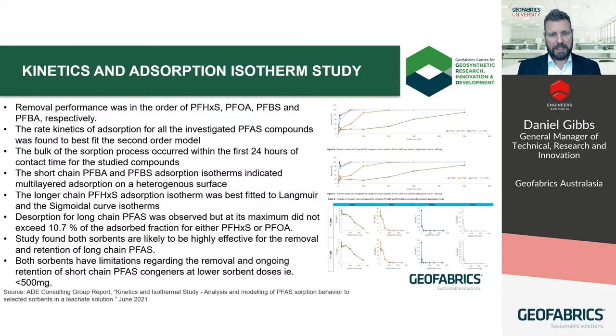We looked at 2 different grades of the same product, one with a slightly lower overall surface area. And the study involved things like reaction rates, equilibrium times using increasing amounts of activated carbon, desorption rates using pure water, etc. It's worth noting that the maximum addition rate of the activated carbon in this study was just 0.5 gram.